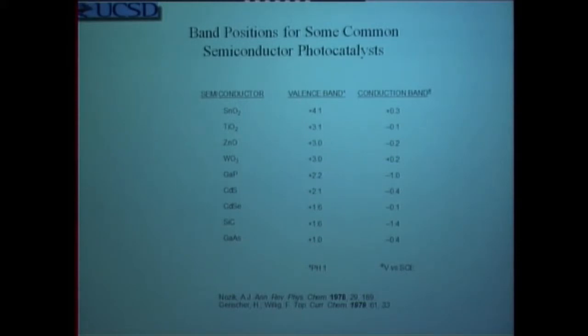So notice the titanium dioxide, the second entry, has an oxidation potential of +3.1 volts. That means any molecule that has an oxidation potential lower than 3.1 volts will be oxidized in the excited state of titanium dioxide. The conduction band is given as well in the right column. And here you see that for titanium dioxide, a reduction potential of -0.1 volts is obtained. That means it's possible to reduce as well.